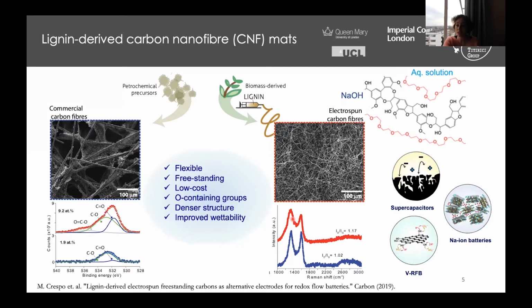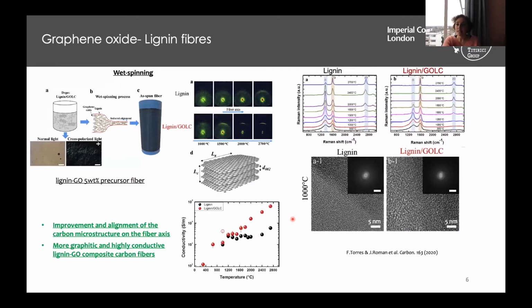But one of the most important things, or the major limitation that we have in these lignin fibers, is the conductivity. If we combine lignin with graphene oxide, the graphene oxide helps and aligns the chains of this very disordered lignin. That means that when the fibers are carbonized, we are able to obtain an improvement in the carbon microstructure with more graphitic domains and highly conductive lignin graphene oxide fibers.